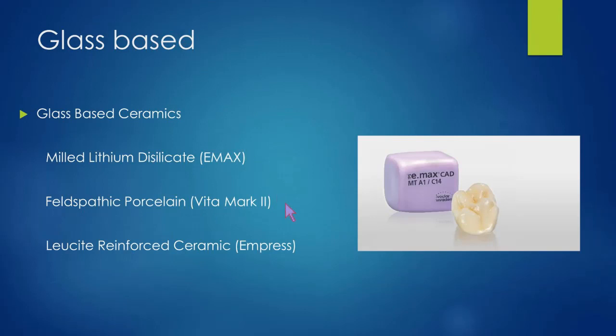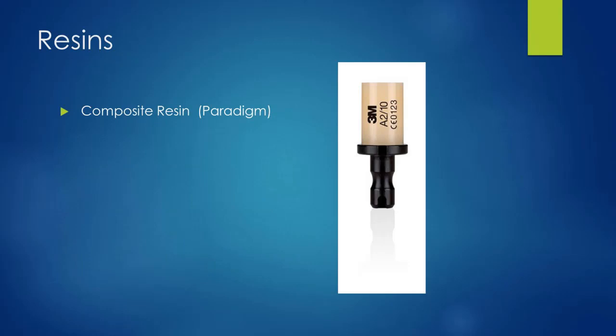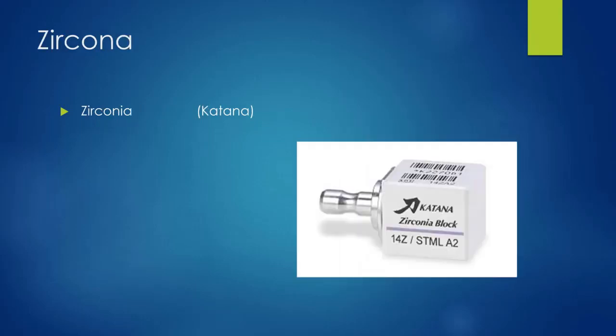So again, the glass-based ceramics, just as a review, we have EMAX or lithium disilicate, we have lithium silicate, we have feldspathic porcelain like Vita Mark II, we have lucite reinforced ceramic like Empress, all available for milling. Again, most of these did require going into a secondary oven, and when thinner we would see some chipping and breaking, and certainly not holding up as well as a lot of the other materials that we're using now. In the resins, again, like Paradigm, low luster, lower strength. So really we started using these mostly for temporary type restorations and for inlay restorations in the posterior, but not using a whole lot of these pure composite resin materials.